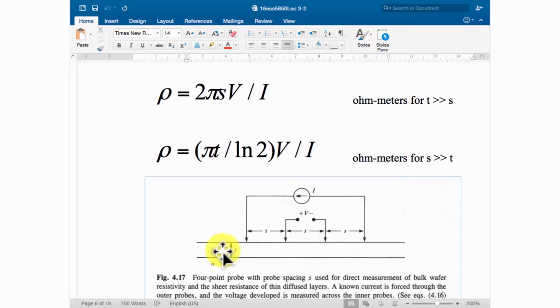When the thickness is pretty thin compared to the distance of your 4 probes, the probe distance is around a millimeter, a couple millimeters to centimeter range. So, for example, if you have only like a 500 micron thickness, it's pretty thin compared to the probe distance. You can plug into the second equation. In the second equation, the resistivity will be some kind of parameter times your voltage over your current. However, if you have a thick substrate, for example, you want to measure the total resistivity of a 500 micron thick substrate, 500 micron is similar to your probe distance. In this case, you need to plug into the first equation to get the resistivity.